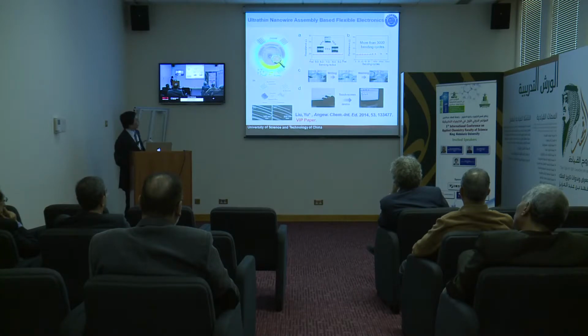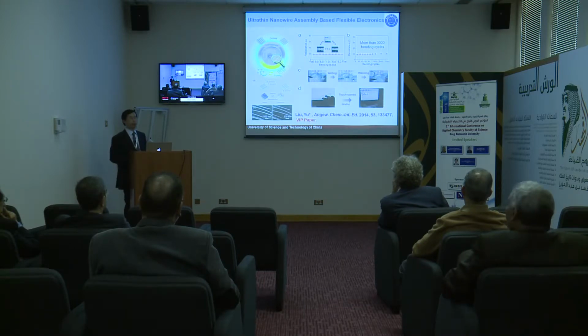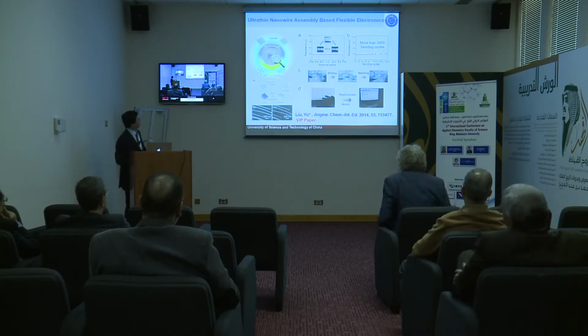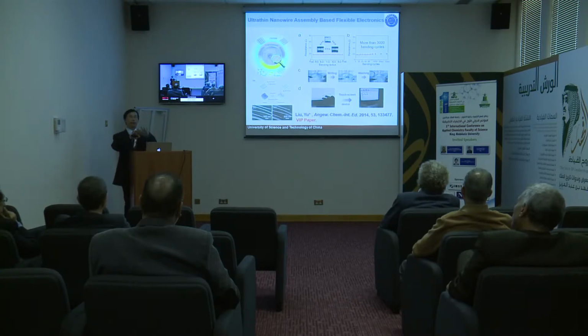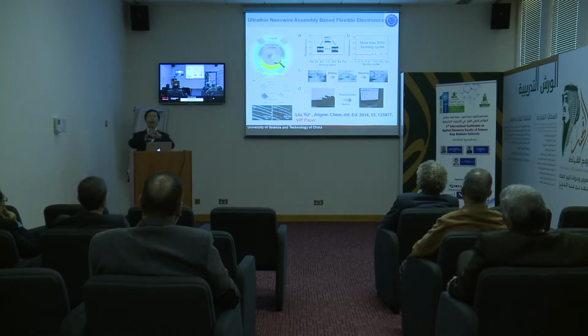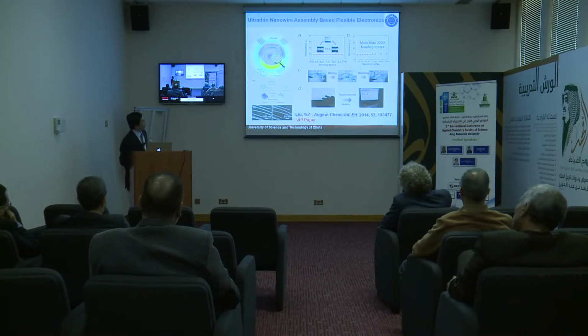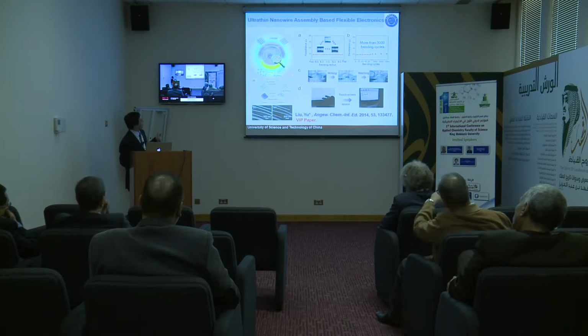Now we think about how to make a more stable material. We use the silver nanowires. We mix the silver nanowires together with our tellurium ultra-thin nanowires. You can make a nanowire network system. After etching the tellurium nanowires, you leave this silver nanowire network here, so that you can get a totally transparent silver nanowire network. Very thin, and they are highly transparent. So then you can get quite flexible. Even if you bend this thin film more than 300 bending cycles, you can keep excellent conductivity for